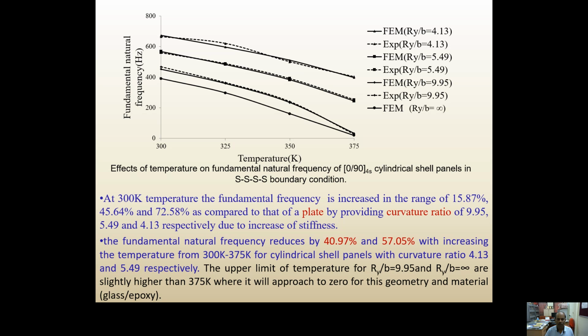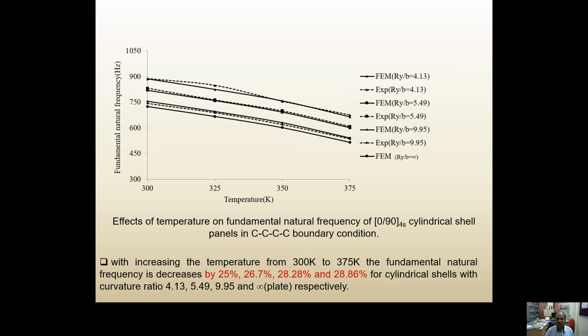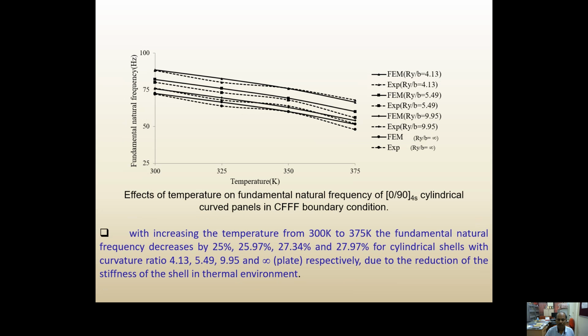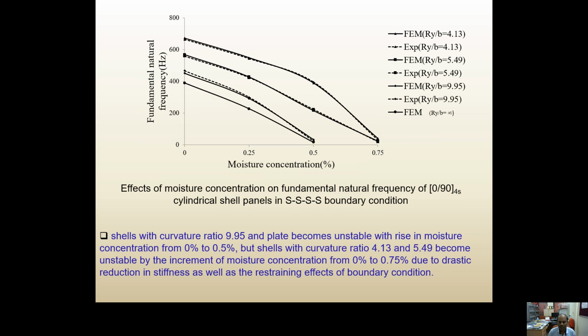Similar studies have been carried out with clamped boundary condition. The frequency also reduces, though the clamped frequencies are significantly higher in comparison to the simply supported shell panels. The frequency is reduced with the increase of temperature. Similarly, for cantilever cylindrical shell panels, the frequencies are much less in comparison to the other simply supported and clamped shell panels, and the frequencies reduce with increase of temperature, though of different percentage.